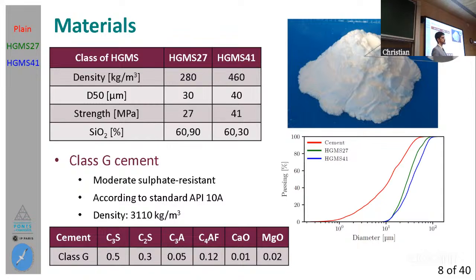First, the very low density of 280 and 460 kilograms per cubic meter, the mean particle size of 30 and 40 micrometers, then the strength, which gives them the name: 27 megapascals for HGM27, 41 megapascals for HGM41. Then we have the content of silica, which is high in both of them, and this is related, if you remember, to the pozzolanic activity, which is around 60% for both of them.